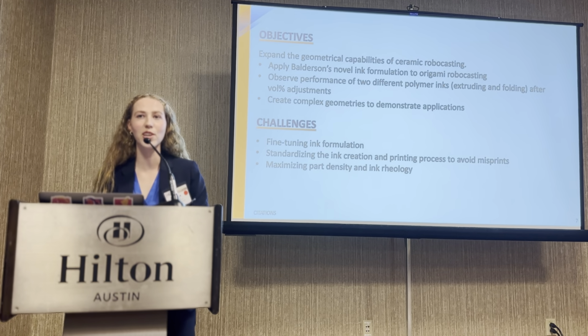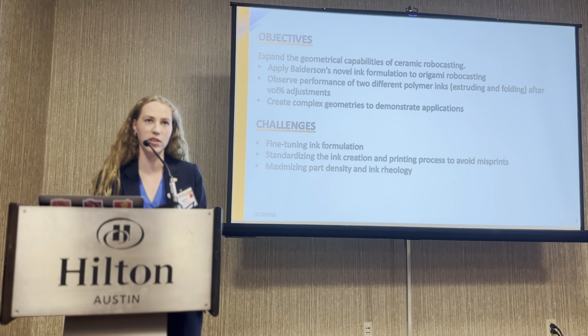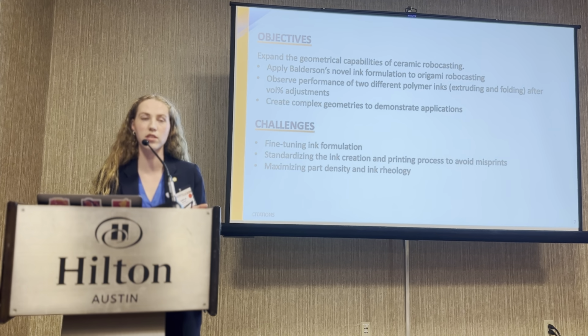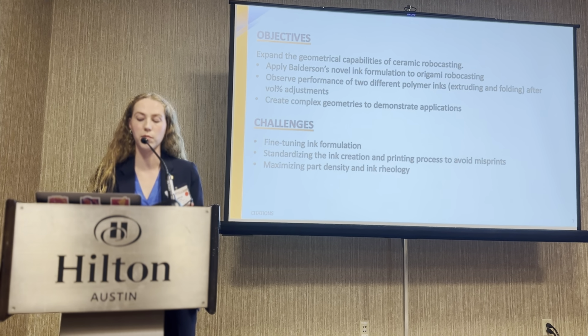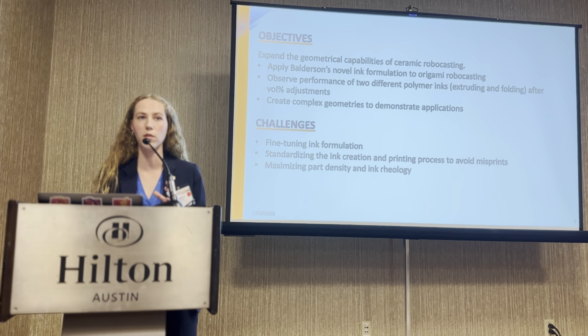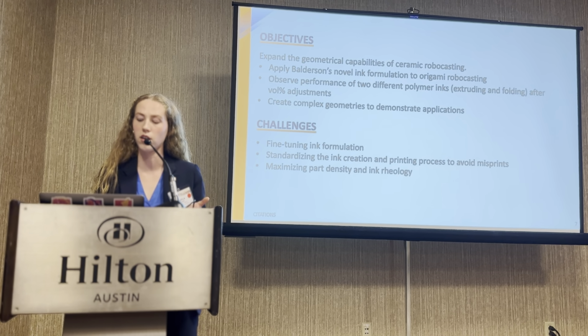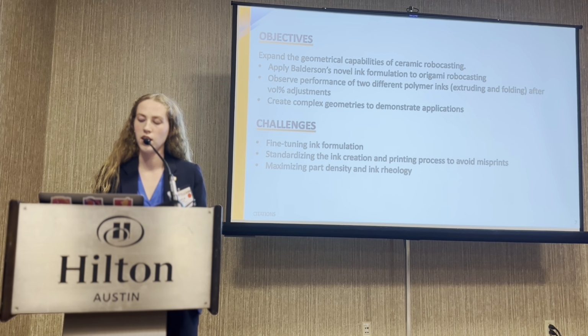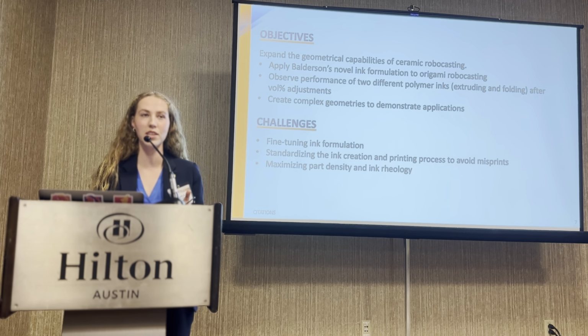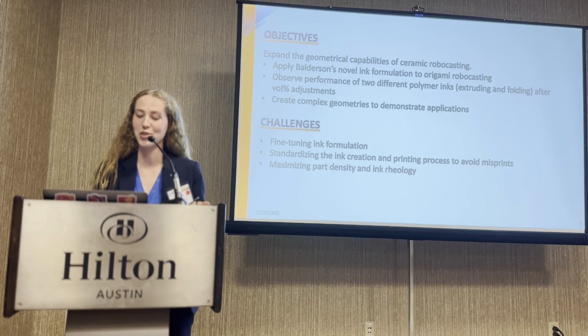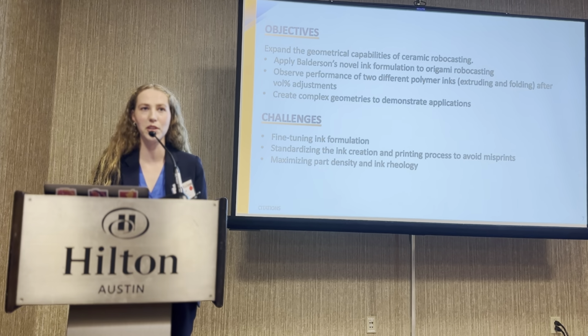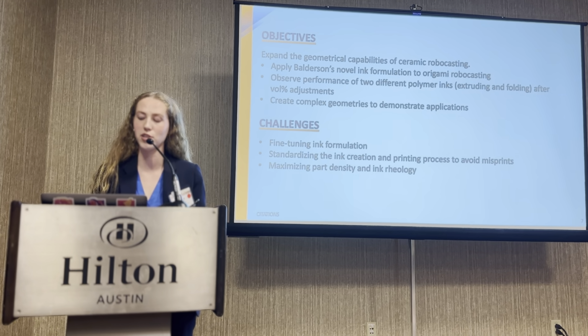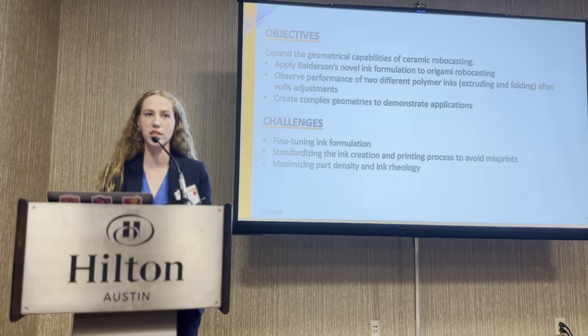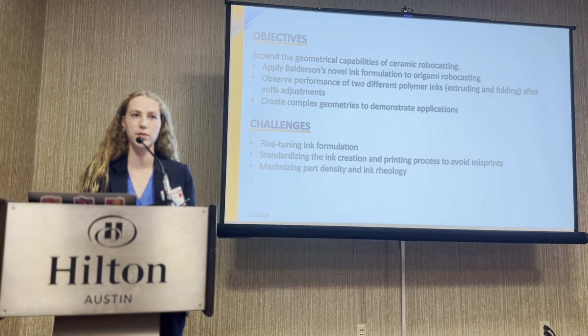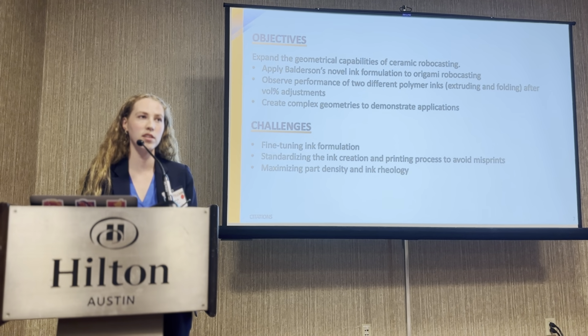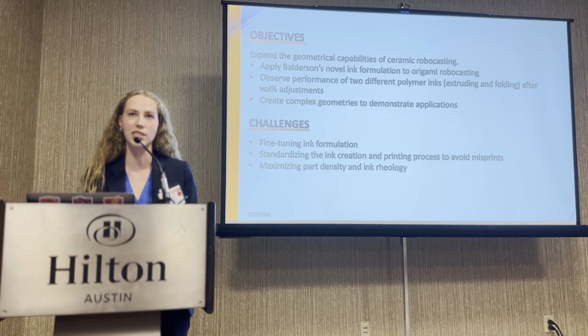For our projects, the objectives on the macro scale: increase geometric possibilities for this method. I used Balderson's novel ink formulation and applied it to origami robocasting, and then I compared two different polymer binders, a polystyrene and a polyethylene oxide, at different volume percents. Then I just wanted to demonstrate the geometric possibilities while working with the challenges of fine-tuning that ink formulation, getting it perfect for printing and manipulation, and also standardizing these processing and printing steps to be able to scale it up for identical prints. Finally, we wanted to optimize the properties of the finished components, properties like density.